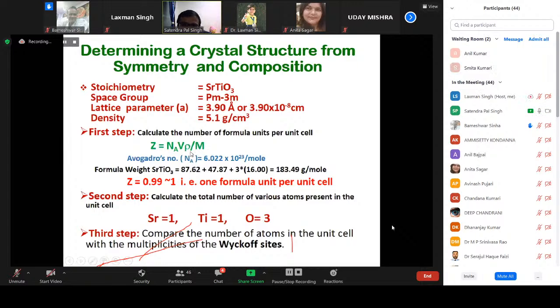If you calculate here using the formula, we can calculate the Z, and the Z value comes around 0.99, that is close to 1. That means in the unit cell, there is only one formula unit. That means there is only one strontium, one titanium, and 3 oxygens. So the unit cell consists of this. How many atoms? 5 atoms: 1 plus 1 plus 3. Now we know the number of atoms in the unit cell.